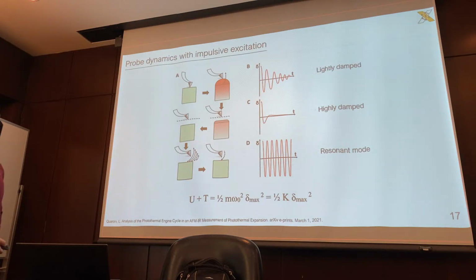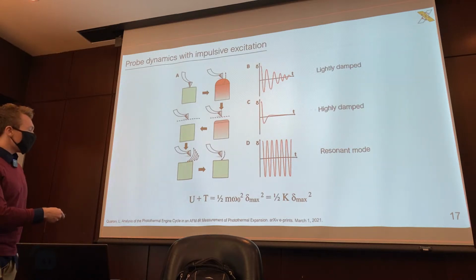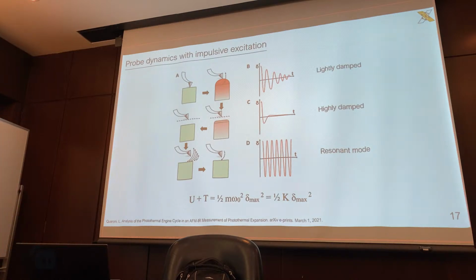In our case, we're using a resonant mode where we're using the actual frequency of our laser to excite the material, which causes our cantilever to resonate at its resonant frequency. And so we never see this ring down at all, but we keep it in its resonant mode. And this actually increases the sensitivity of our instrument overall. So you can see that the overall energy, which is potential energy and kinetic energy, is a function of the mass of the cantilever times the resonant frequency of the cantilever times our maximum deflection.